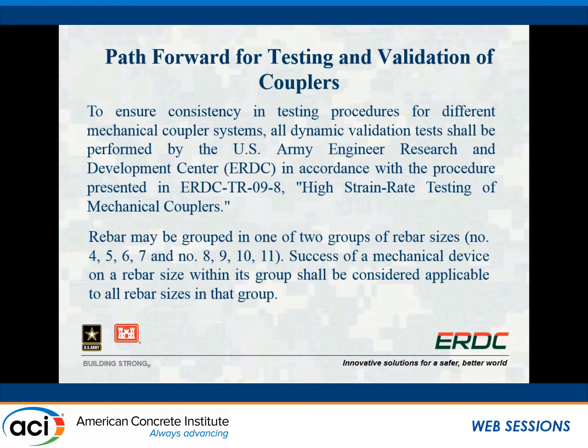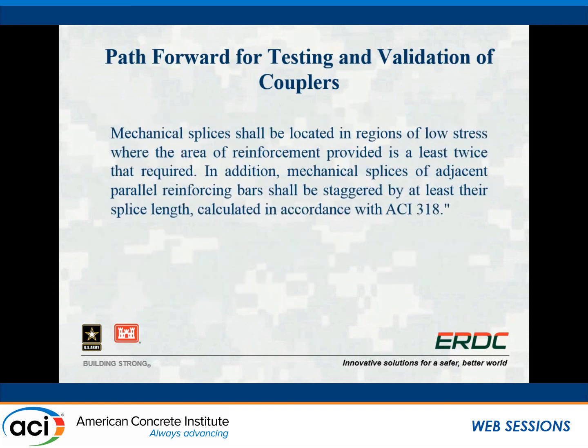And so those bars can be tested to determine whether they're applicable, and then the results for that coupler can be basically extrapolated over the other bar sizes in those groups. And then, like anything we would do with a mechanical coupler or lap splice or anything, we try to put it in low stress zones and stagger the locations of couplers because there's still a failure point of weakness and discontinuity. And so we try to do this to help with redundancy considerations.